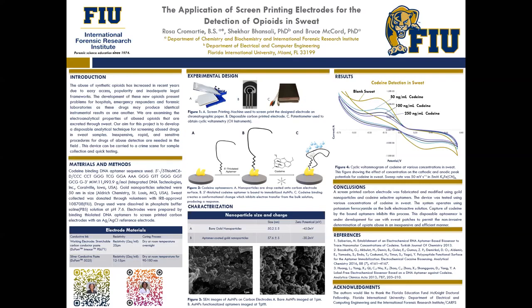And in figure 4, which is a part of my results, we see a cyclic voltammogram of various concentrations of codeine, where it shows a signal drop as codeine increases. So the more codeine that is present, it blocks the reaction binding of ferrocyanide. In other words, the binding of codeine interferes with the ability of ferrocyanide to access the aptamers bound to the gold nanoparticle for electron charge transfer exchange.